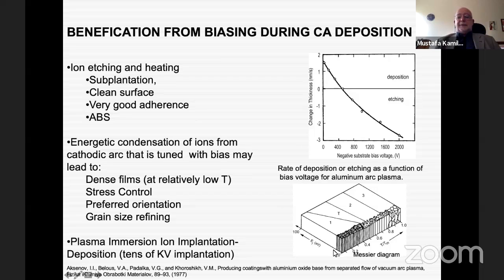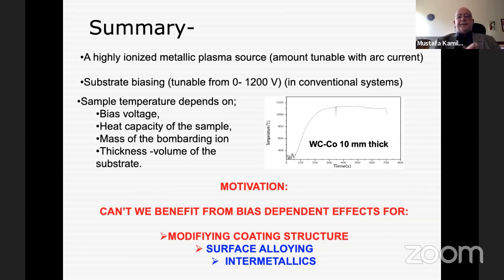But on the other hand, we can change the story by the application of an additional energy that we apply through biasing. So when we apply biasing, we can have dense structures at low temperatures. This is one of the biggest benefits of biasing in PVD coatings. So in summary, you can attain a highly ionized metallic plasma, the amount of which can be tuned with the arc current. We have a substrate biasing.